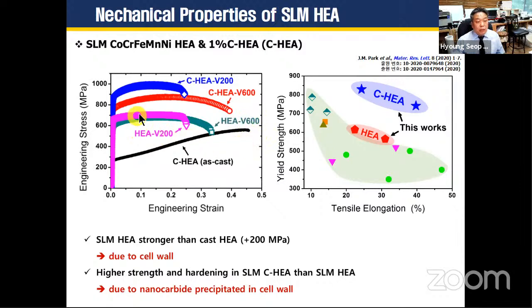The SLM processed high entropy alloy shows very high yield strength compared with that just cast one, and low elongation compared to the cast one. But this low elongation is still good enough for structural part applications. This number, 200 or 600, represents the laser scanning speed, millimeter per second. The SLM processed 1% carbon-added high entropy alloy exhibits even higher strength and better ductility than that without carbon. 200 millimeter per second, very slow scanning, produced more coarse carbide, so strength is high, but ductility is low.